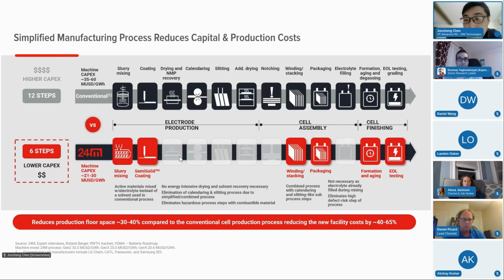How does the SemiSolid work? Our process is quite different compared to the conventional process. We're mixing electrolyte together with the powders to form a clay-like, cookie-dough-like slurry with a high yield stress. And then that high yield stress non-Newtonian fluid is piston pressed onto the current collector. Then after the casting, we go directly to the winding and packaging because the electrolyte is the processing solvent. And from mixing through casting to assembly, it's minutes of operation.